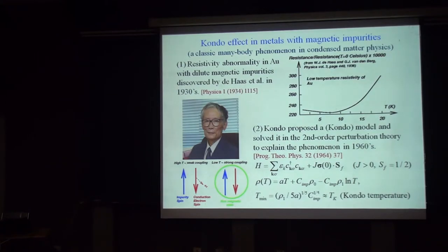And then, of course, people did a lot of experiments and eventually they realized there are magnetic impurities in the gold. In 1960, Jun Kondo from Japan, he proposed a Kondo model. Looked like this is free electron Hamiltonian. Then you add coupling term, which is magnetic impurity spin moment coupled with the conduction electron spin moment. And this is anti-ferromagnetic coupling. Then he solved this model using second-order perturbation. And then realized that at low temperature, in addition to this linear dependent term, and this residual resistivity, you have this term which is proportional to log temperature.